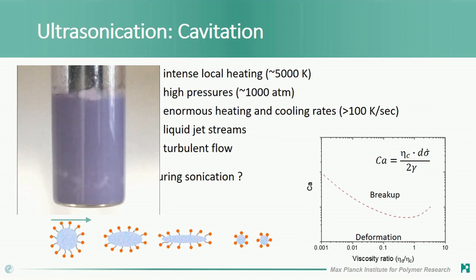So there's a trade-off between having a lot of low energy bubbles or having a few high energy bubbles. And at the end of the day, if you sonicate your sample for long enough, you will reach more or less the same steady state condition, but it will take different time, and it might not be exactly the same equilibrium that you will form.